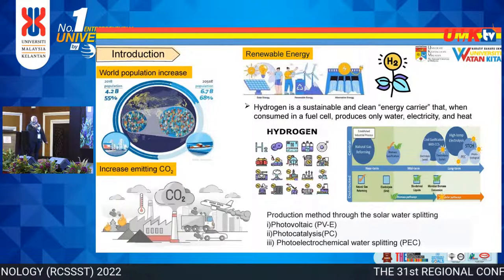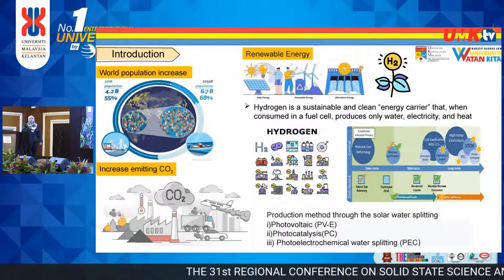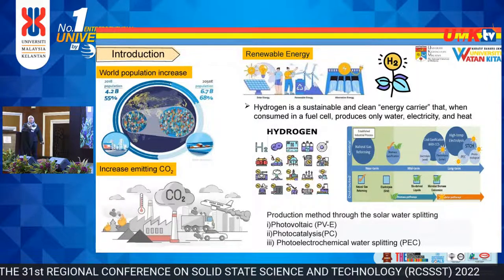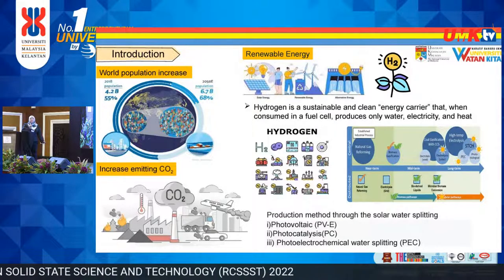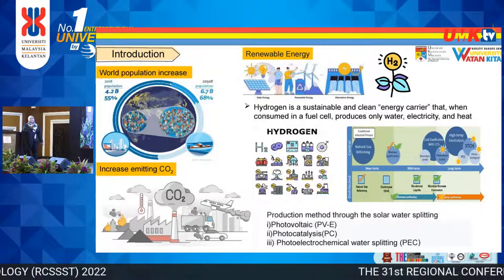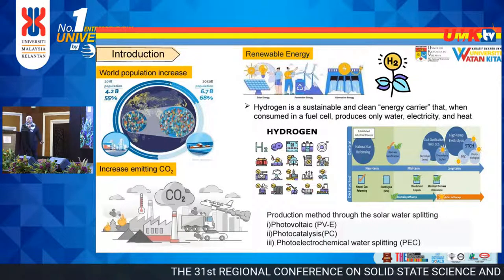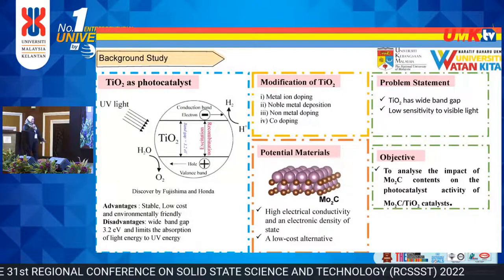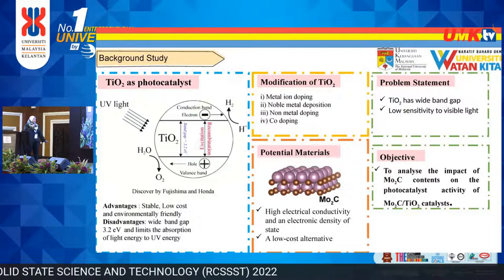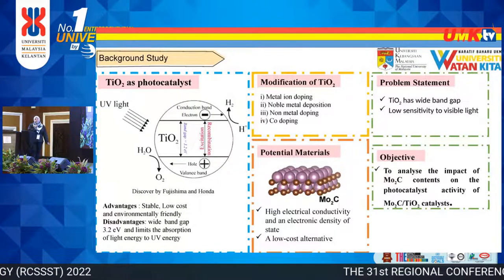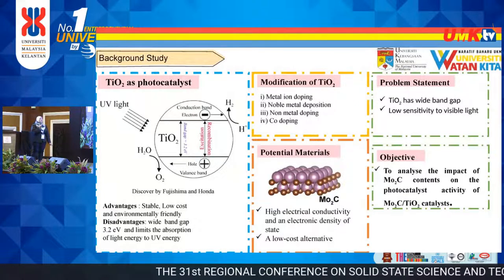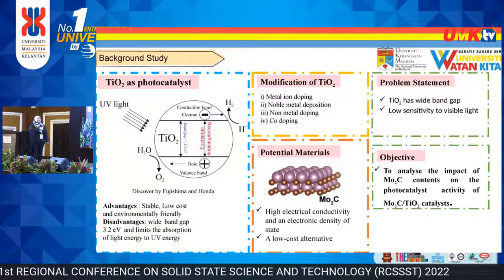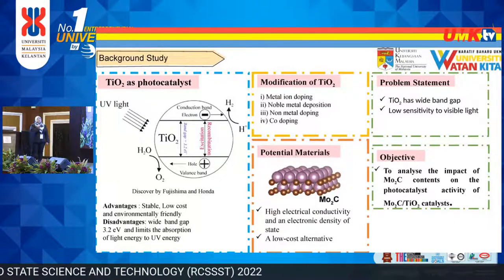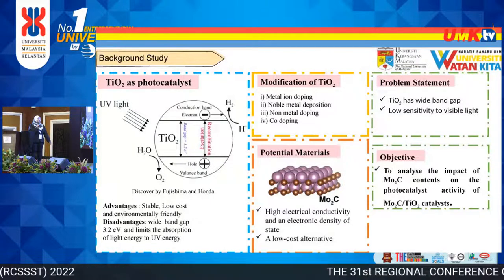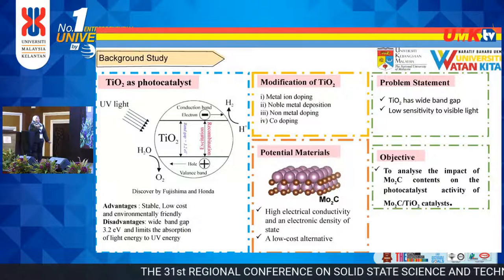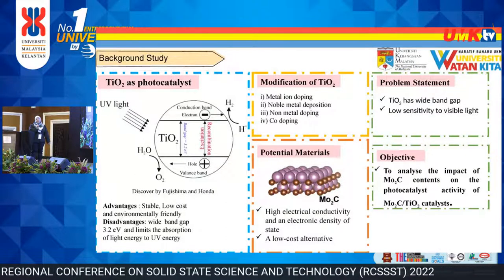As a background, TiO2 was found by Fujishima and Honda in 1972 as a photocatalyst for splitting water molecules into hydrogen and oxygen. Until now, titanium dioxide is still the most desirable and studied material due to its advantages of being stable, low cost and environmentally friendly. However, TiO2 has limitations such as a wide band gap and limited light absorption because it absorbs only UV energy. Researchers have made many modifications such as metal ion doping, noble metal deposition, non-metal doping and co-doping. Today I will focus on a composite heterojunction with molybdenum carbide, because molybdenum carbide is a high electrical conductivity material with high electronic density of states and is also a low cost alternative material, to overcome the problem that TiO2 has a wide band gap and low sensitivity to visible light.